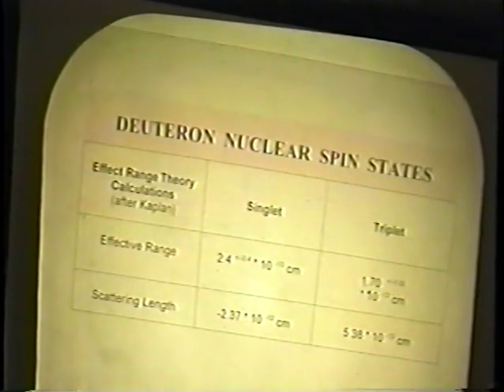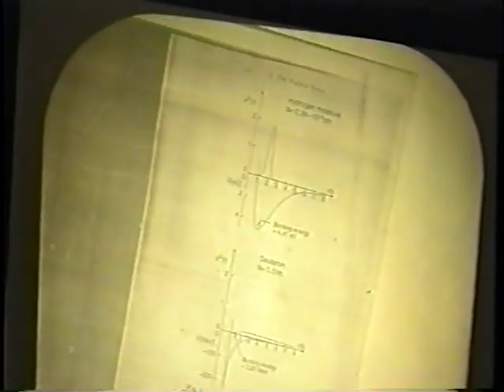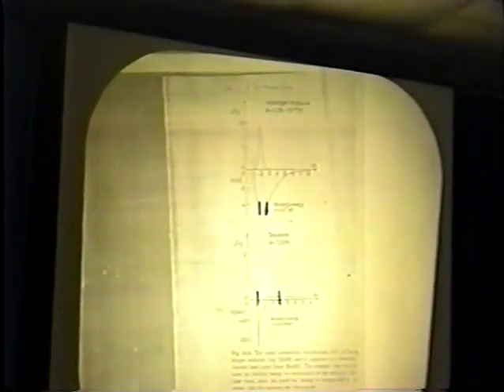Deuterium is probably one of the most fragile nuclei we know. As you know, the proton and the neutron in the deuteron are quite far separated, if you look at the relative width of the nucleon in comparison to the hard cores, as opposed to the hydrogen atom. In the hydrogen atom, the two nuclei are well fixed. In the case of the deuteron, they're far apart. So one of the reasons people never thought about deuteron production is that they photodecompose at 2 MeV, and they're very fragile.